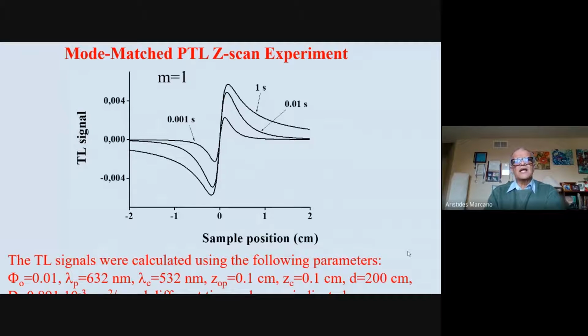If you consider that m is equal to 1, it means that this is the mode match situation, and you get the typical Z-scan experiment. The Z-scan experiment means that you move your sample around the focal point, and you will get this particular shape that looks like the Z of Zorro. That's the reason it's called Z-scan. It's a very popular method for detection.